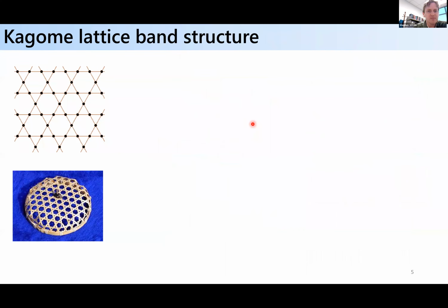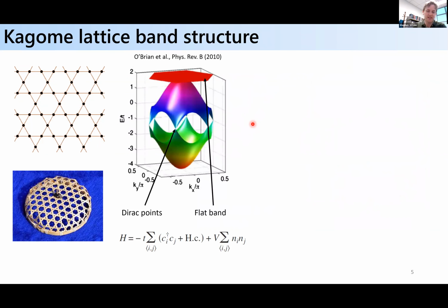But when one thinks about the electronic degree of freedom, basically in terms of the band structure, kagome lattices also have long been of interest because if you just look at the simple single orbital tight binding models, then you get a band structure that has a coexistence of a couple of different interesting features. One being topological physics associated with Dirac points in the spectrum, but also potential electron-electron correlation physics, because you can realize flat band physics, right? So you can populate flat bands and potentially promote correlation effects. And so you could potentially have this interplay between non-trivial electronic topology, but also electron-electron interactions.